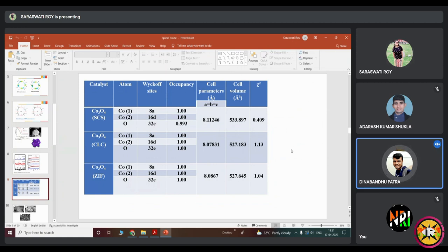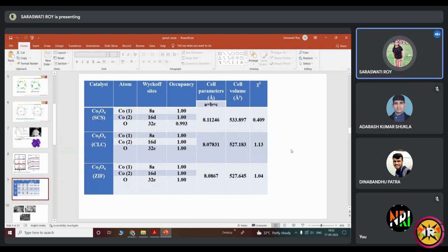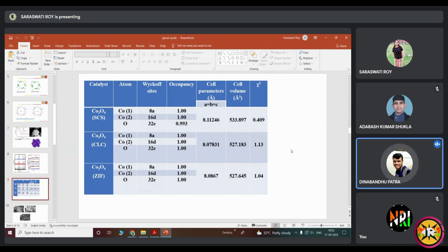Because in Co3O4 the particle size is less, right? Yes. So the magnetic property also will be less, and when the particle size is less, then the disordered surface structure will be there. So the oxygen vacancy formation also will be more. Okay, no, I haven't done this. This is not related to the magnetic property, I'm just saying that to create more oxygen vacancy in a smaller size sample, it is another kind of proof that oxygen vacancy is there. I understood, but no, I haven't done this. Okay, thank you.